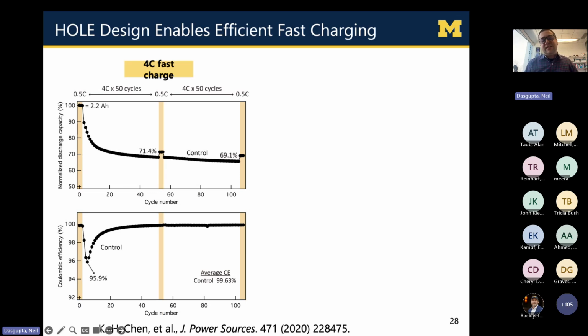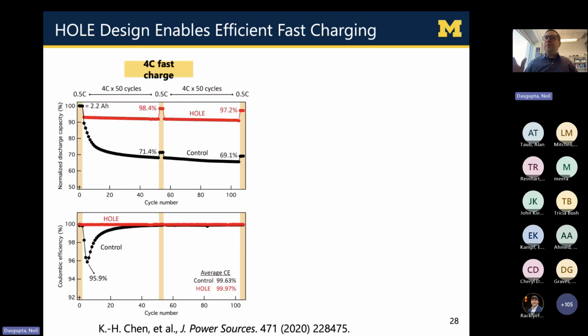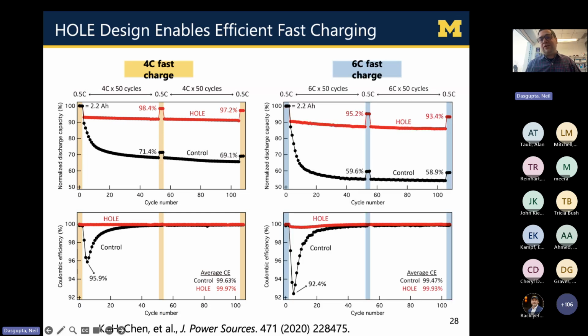And in fact, even as you can see in the bottom in our coulombic efficiency, which is how much charge we get back compared to how much charge we put in, even within the first 10 or 20 cycles, we're really damaging and degrading the battery a lot. Remarkably, when we look at the hole electrode, we were able to eliminate a lot of those losses in the early fast charging cycles, and we're able to maintain over 97% of the accessible capacity after 100 4C fast charge cycles.